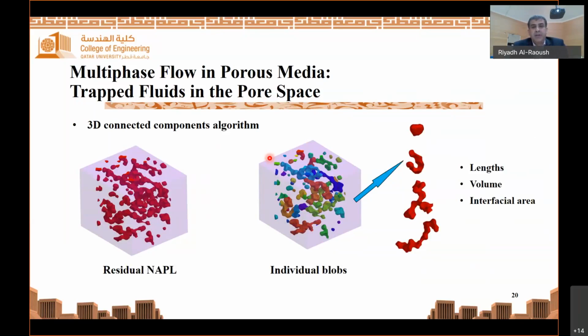This is another three-dimensional image. It's an outcome of a computed tomography experiment that we conducted. We looked at the trapped blobs in the pore space. The size of the sample is 1 millimeter by 1 millimeter by 1 millimeter here. This image shows the distribution of individual blobs, and you can see these are identifications of discrete or individual blobs. From this system, we can obtain parameters such as length, volumes, directions, and these can be used as input to models that predict processes such as mass transfer.